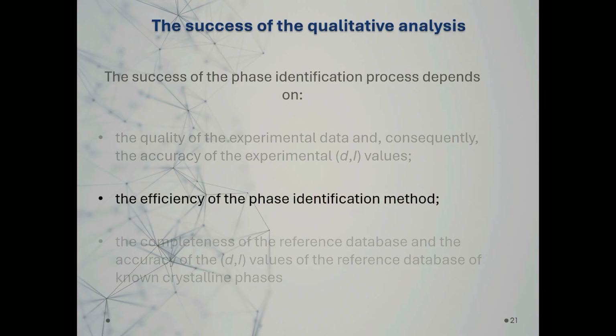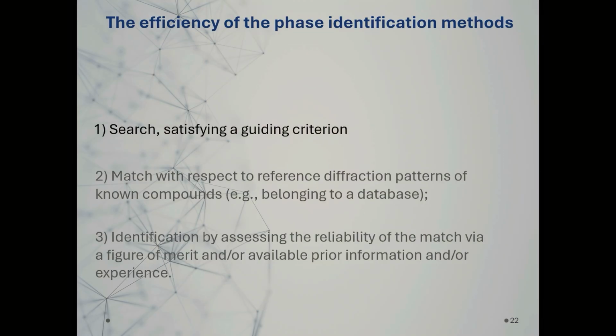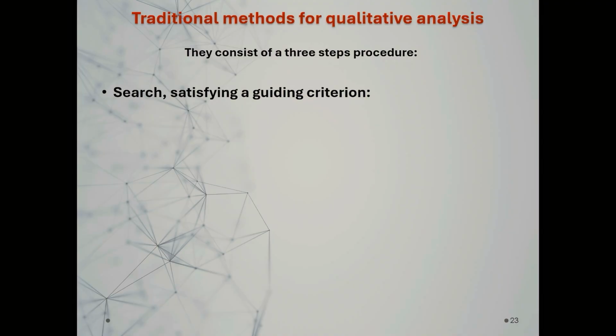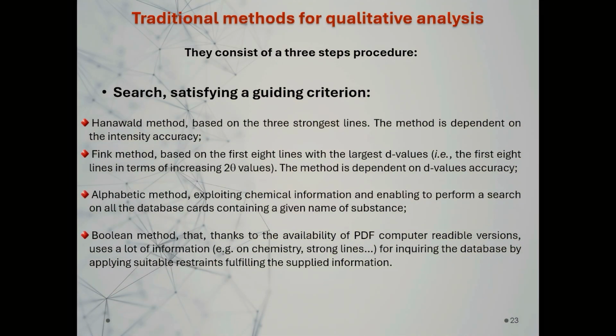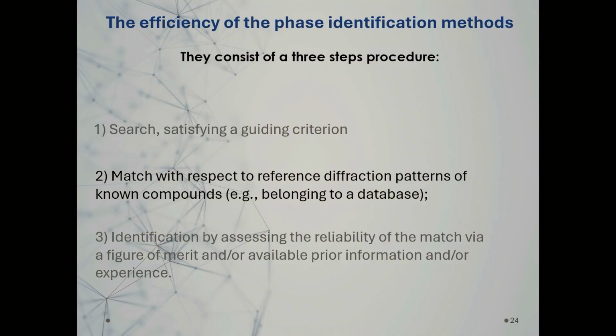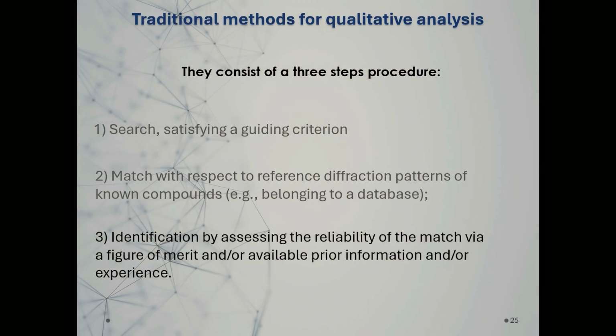Another aspect for the success of the qualitative analysis is the efficiency of the phase identification method. This is a method that first consists of a search, satisfying a guiding criterion. We can have more methods. The Hanawalt method is based on the three strongest lines. The Fink method is based on the first eight lines with the largest d-value, or the alphabetic method, and so on. And when we have the powder diffraction pattern reduced to d-hkl values, then we have to match these values with the ones belonging to a database. So we have to match.